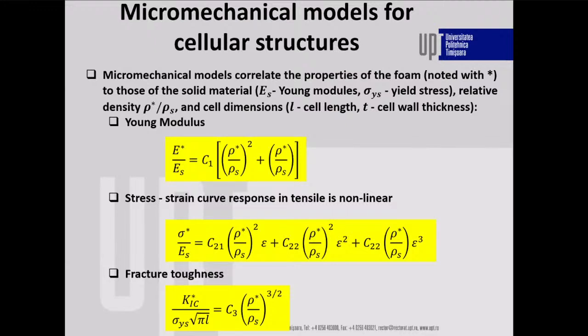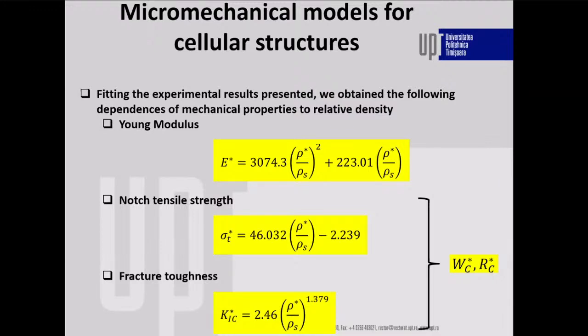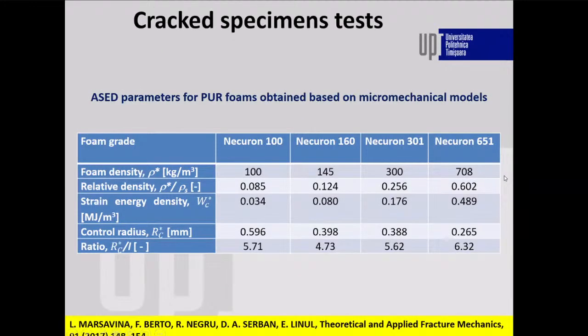Such micromechanical models exist for Young modulus, for the stress strain curve, and for fracture toughness. With our experimental data, we found some relations for our particular polyurethane foam, the expression of Young modulus, of notch tensile strength, and of fracture toughness. We used these values to fit the critical strain energy density and the control radius, and you can see the results here. The strain energy density increases with density, while the control radius decreases with increasing density.